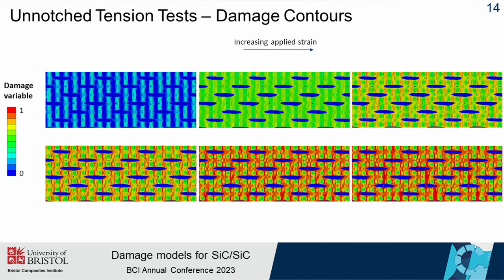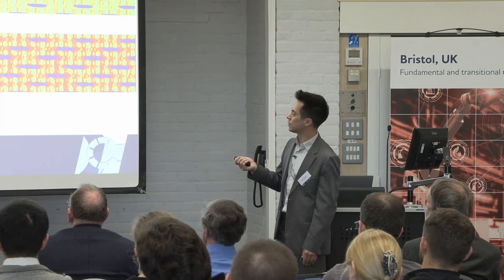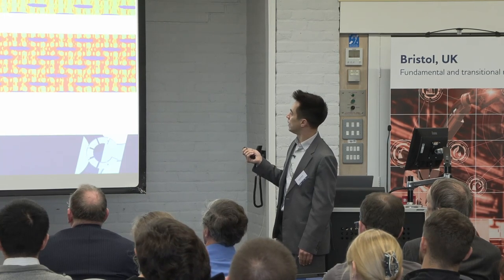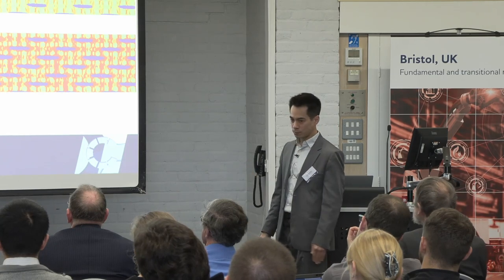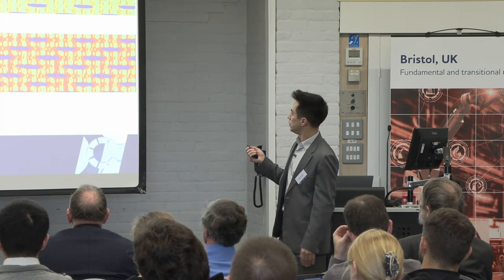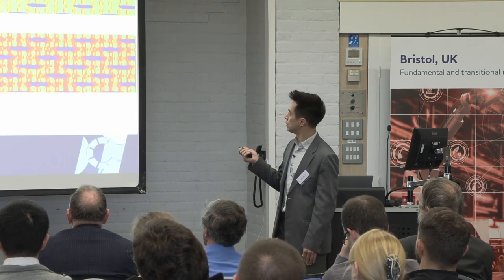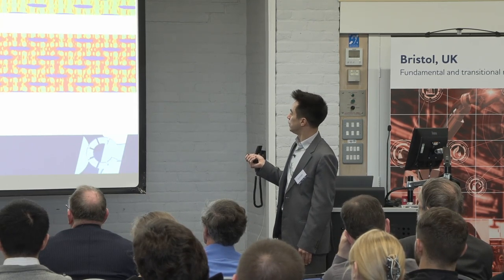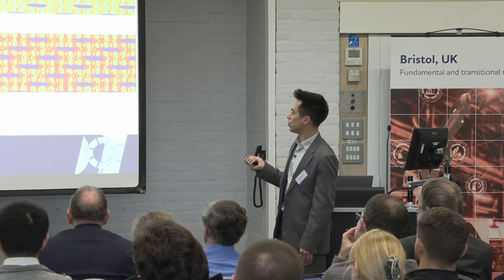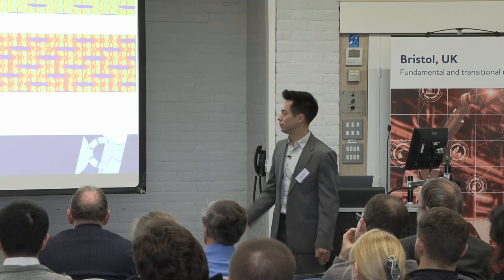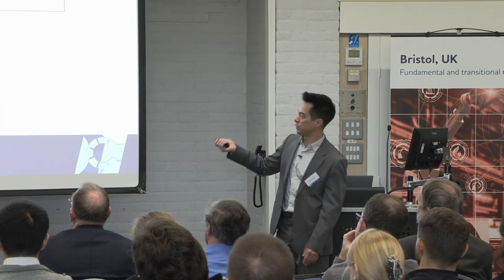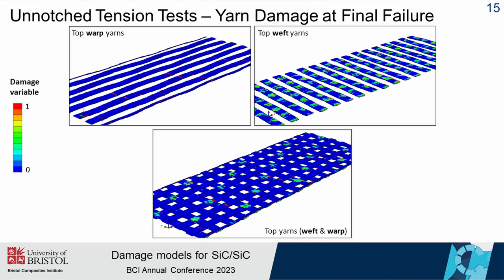So here we're going from left to right, and then first the top row, and then the bottom row. Seeing the evolution of damage in both matrix, bulk matrix and yarns as we increase the applied strain. So initially it's all elastic, and then eventually you see the damage kind of concentrating along the bulk matrix and the weft yarns. And eventually you end up with, I'm not sure if you can see it here, but there's actually yarn failure, okay? And similar results shown in a different way, just showing the top yarns at that final failure.